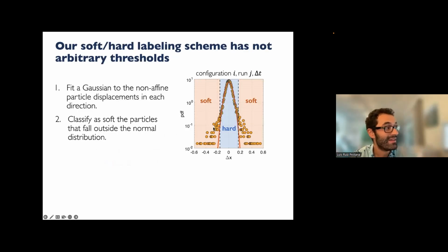So what we are going to do is take the probability distribution of displacements for X, Y, and Z. We are going to fit a Gaussian to the displacements, and we are just going to classify particles outside that, that don't fit the Gaussian, as soft, okay? There are no moving parameters in this scheme. We are just fitting a Gaussian to the displacements of the whole population of particles at some time. We don't have a threshold.